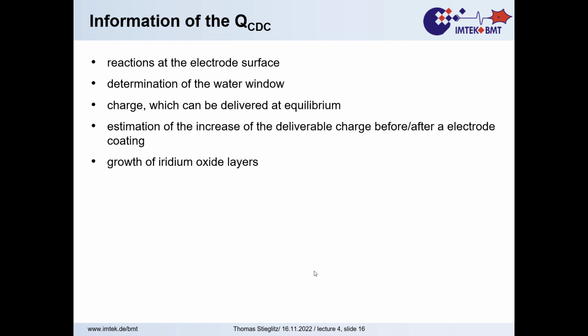So is there platinum dissolution or not? Is there iridium oxide working well, or doesn't it work at all? For us, one very important finding is always: are the electrodes open? If you make microsystems, you quite often have sandwich structures. You put in an insulator, you put in your electrode with a cable, you put a top layer insulator, and you open the top layer insulator to come to the electrode. When the top layer insulator is still closed, you have no electrode.